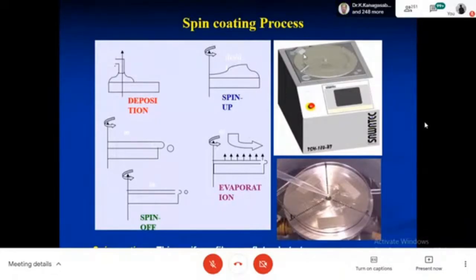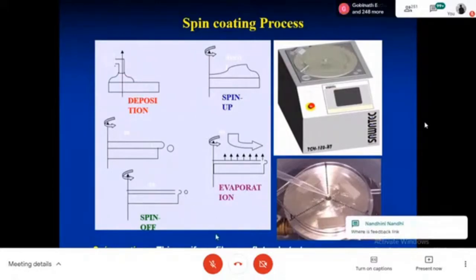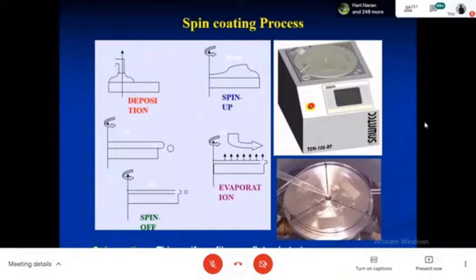The spin coating process involves that you take this solution and allow it to fall on the substrate, and the substrate is attached to the sample holder. It rotates at a very high speed of about 3000 to 4000 RPM, and the liquid falling on the surface gets uniformly dispersed over the entire area of the substrate. Then you have the uniform coating. This spin coating is useful for very uniform coating on flat surfaces. If your substrate is not flat enough, then it will be difficult to have a uniform coating. And after the coating, the solvent is volatile and can evaporate.